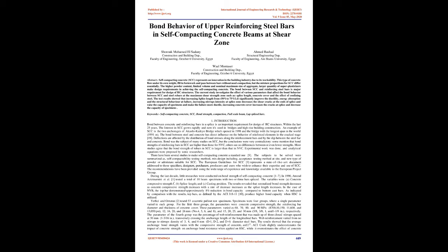the mixture proportions for SCC differ essentially. The higher powder content, limited volume and nominal maximum size of aggregate, and larger quantity of superplasticizers make design requirements important in achieving the self-compacting concrete. The bond between SCC and reinforcing steel bars is a major requirement for design of RC structures.